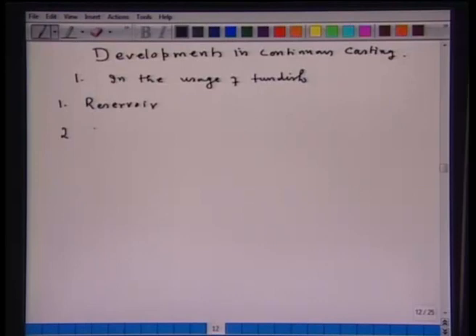Second, it also acts as a distributor — in a multiple strand casting machine, you have four or six tundish nozzles, and the tundish distributes the molten steel to all these strands. Important is that the superheat in each strand should be the same and chemical composition should be the same. In its distribution role, strand similarity is important — when we have strand similarity, all strands will be similar and quality problems will be less. For multi-strand continuous casting machines, the strand breakout chances should be minimized, which is done when the tundish supplies steel of the same temperature and chemical composition to all the molds.